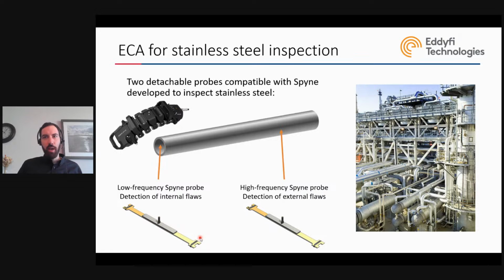So how does it translate into eddy currents? For the same Spyne scanner, we developed two sets of coils. Those at the bottom you see here are just a ribbon of sensors that you can attach to the Spyne. If any of you have been using the Spyne for carbon steel, all you've got to replace is this little ribbon of coils that is now optimized for stainless steel. We repackaged the coils in a different geometry. We use slightly larger coils to be able to penetrate the stainless steel, and we also arrange them in a different topology. We move them to different positions to be really optimized for intergranular SCC in austenitic stainless steel.